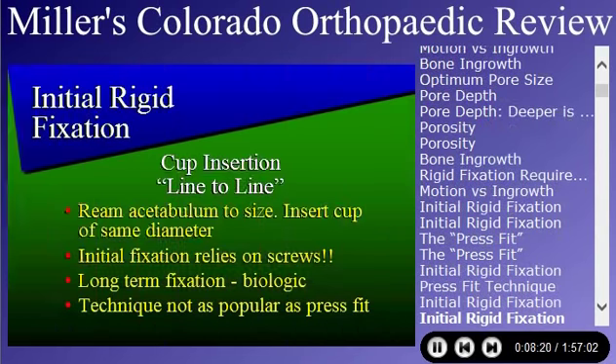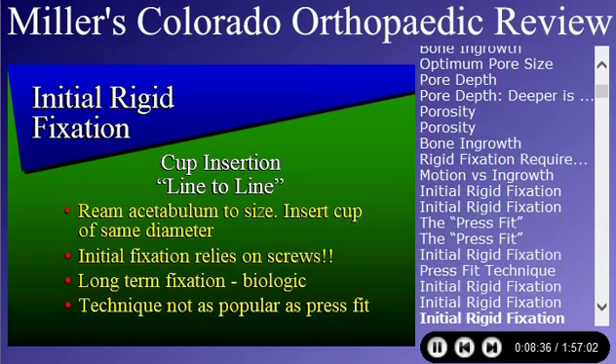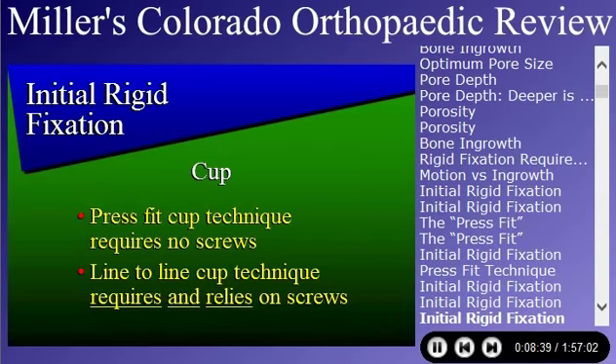Same thing with the cup. You ream the acetabulum to a certain size. You insert the cup of the same size. The initial fixation relies on the screws because that cup is just a hemisphere and it will toggle around, so you have to hold that cup in place. The long-term fixation is biologic, and again, it is a technique that's not as popular as the press-fit because you're relying on the screws. Remember, the press-fit cup technique requires no screws. You wedge it into that tight bone. You hit the rim. That rim gets the compressive hoop stresses, and you don't need the screws. Line-to-line, on the other hand, relies on the screws. If you don't have good screw fixation, that cup's going to toggle and get loose. That's why most people tend to use the press-fit technique for the cups.